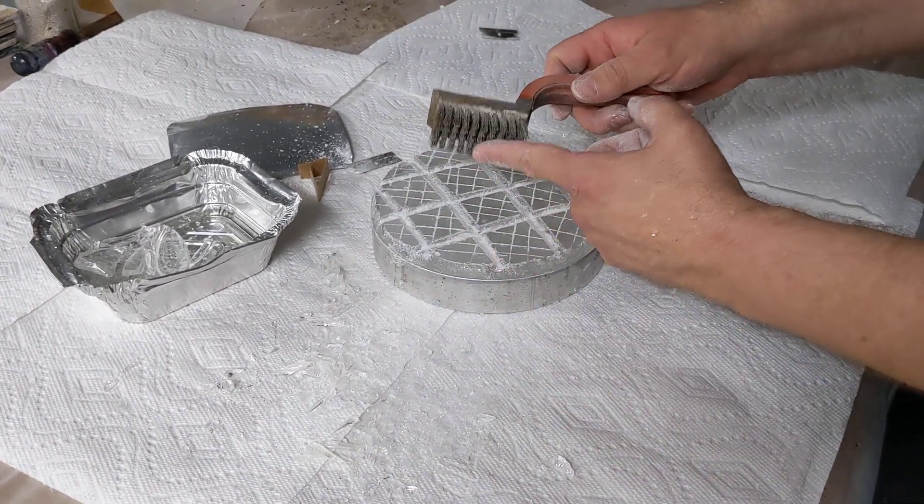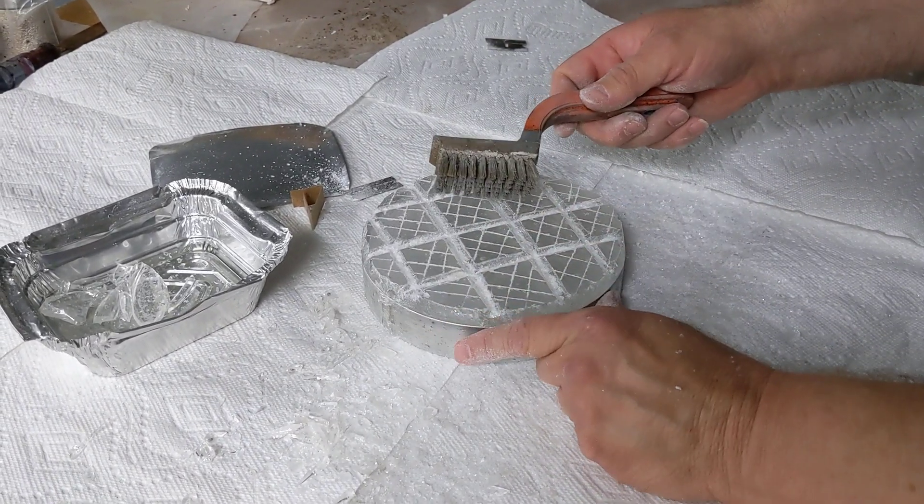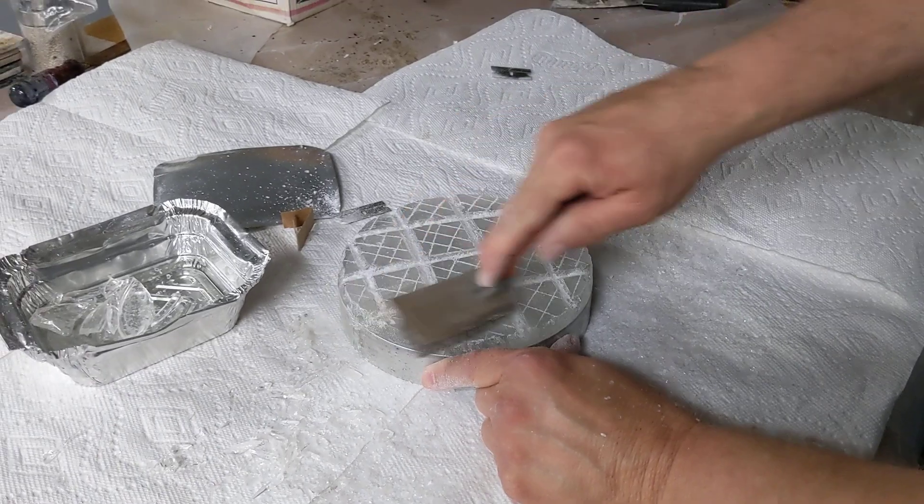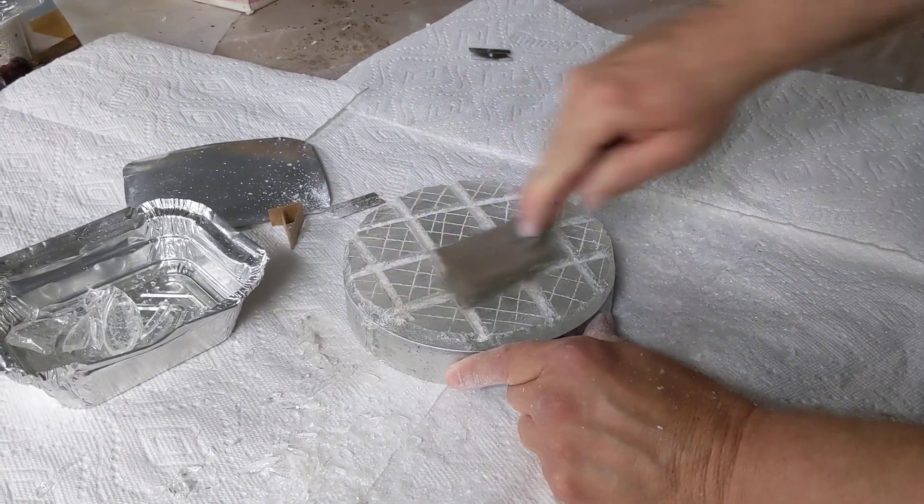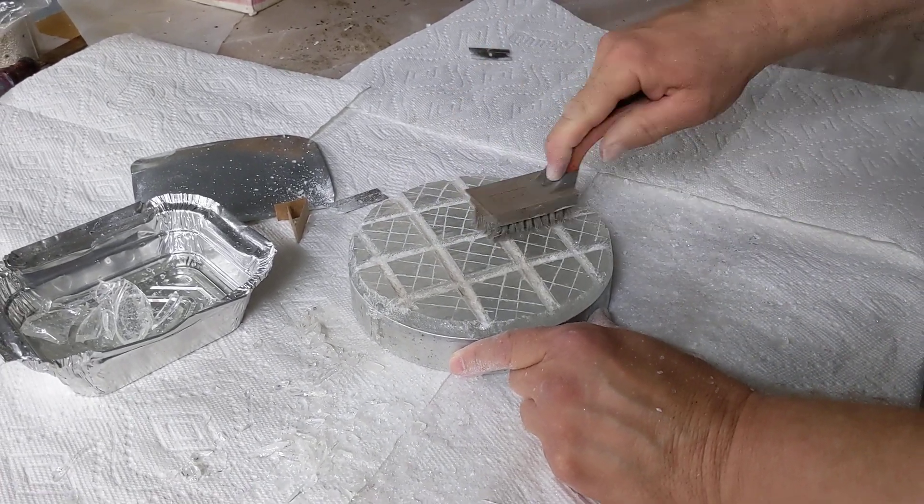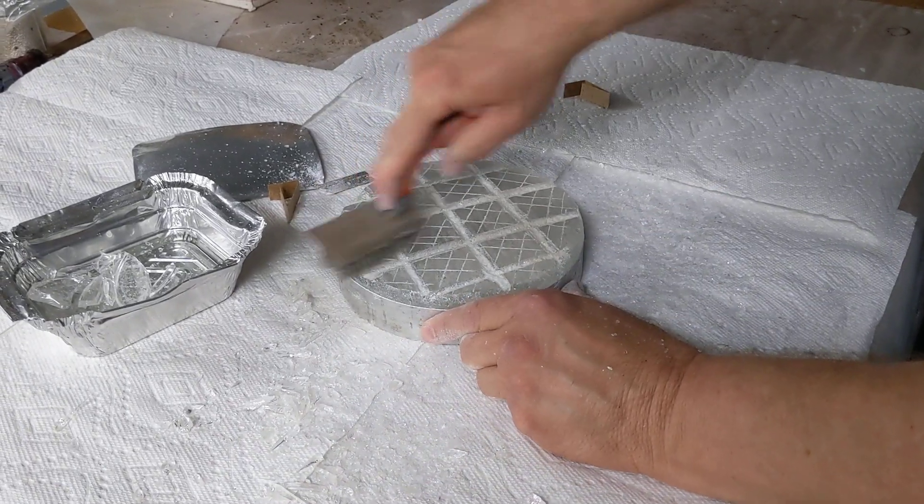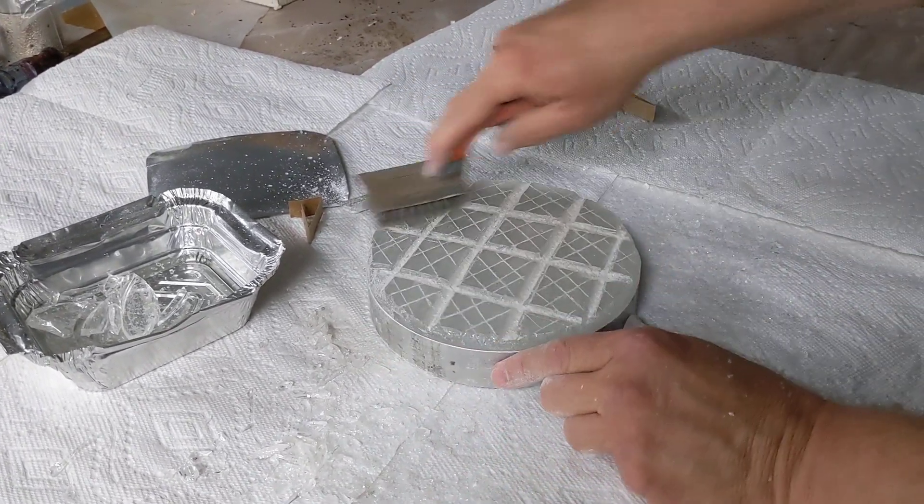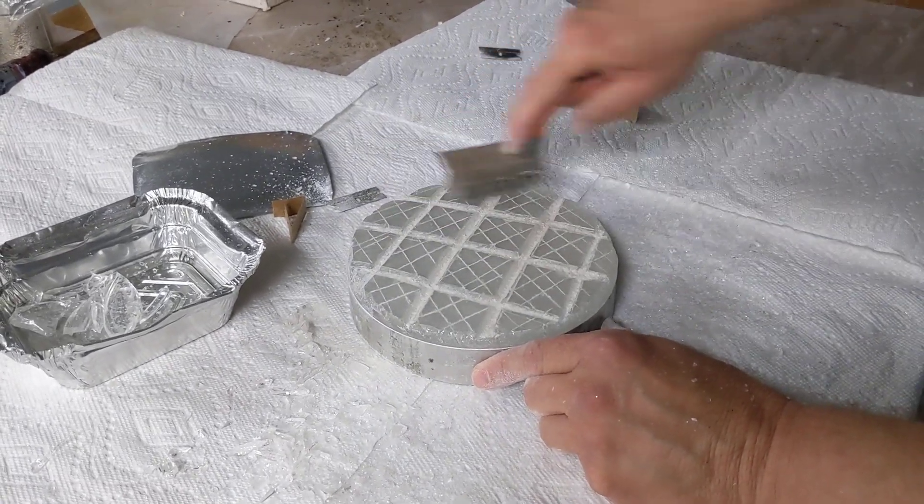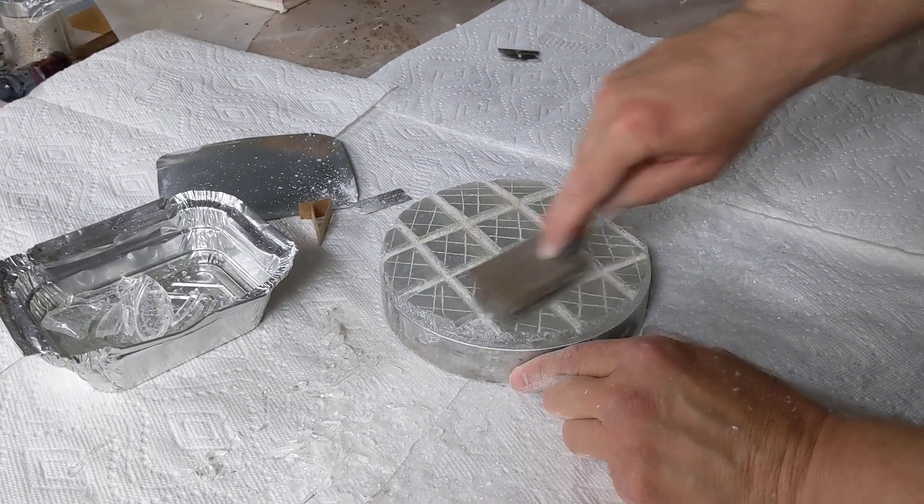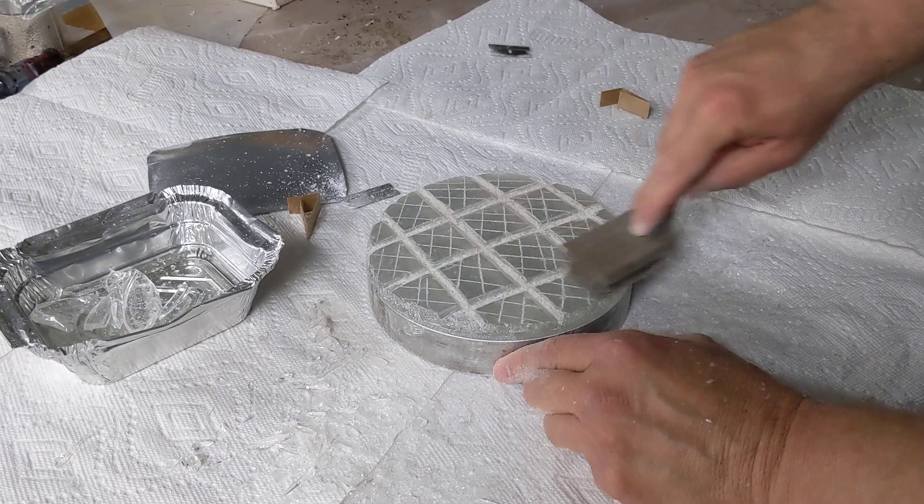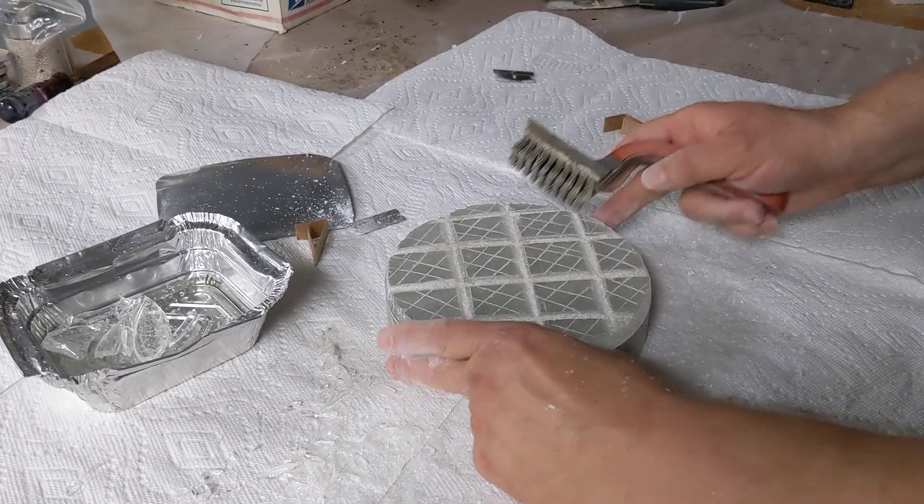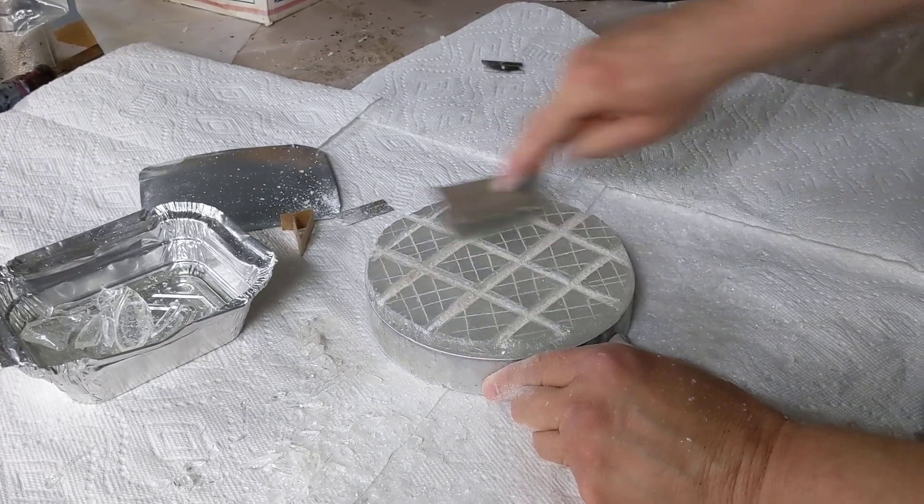Final step is I take a brass brush, brass and not steel, because the brass is softer than the Borosilicate glass and won't scratch it. So if any of the little pieces come out into the polisher, you don't want those to get in the polishing process. So I take the little brush and go to town on this polisher. And the point is to rough up the surface. It naturally has a smooth, shiny surface that isn't right for polishing. You want to rough it up. And this has the effect of putting thousands and thousands of little micro facets on the surface. And again, since this was molded directly onto the mirror's surface in the first place, it's perfect contact. I will cold press this for maybe four or five minutes with 10 or 15 or 20 pounds of weight. Since it's a firm intermediate grade of AccuLap, it won't deform very much. And then this will be ready for polishing action in just a few minutes.